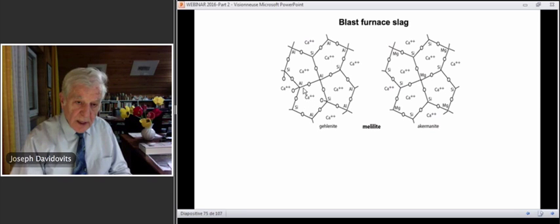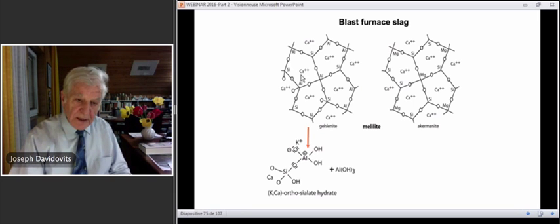It is 2Al, 1Si, silico-aluminate of calcium. The calcium cation is used to balance two aluminum atoms. Akermanite doesn't contain aluminum, only silicon and magnesium. If you subject gehlenite to alkalination, that is the first step of geopolymerization, it is depolymerized into the first small molecule, the ortho-sialate hydrate, Si-O-Al, with the calcium here, and the potassium or sodium here, and it is this molecule that will then interact later. But since we have 2Al for 1Si, and here only 1Al for 1Si, there is precipitation of Al(OH)3, aluminum hydroxide.